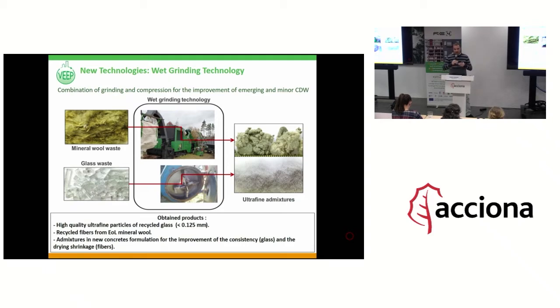This technology is a combination of grinding and compression for reducing the size of this material, in order to employ the fibers and the glass as an admixture in new concrete formulation. From this technology we obtain microfibers and glass admixture in order to provide new properties to the new concrete formulation. For example, the microfiber will reduce the shrinkage, and the glass powder will improve the consistency, the fluidity of the concrete.